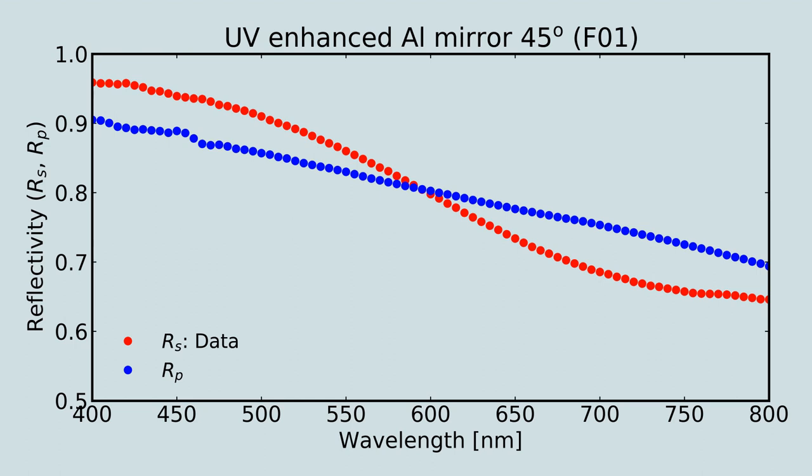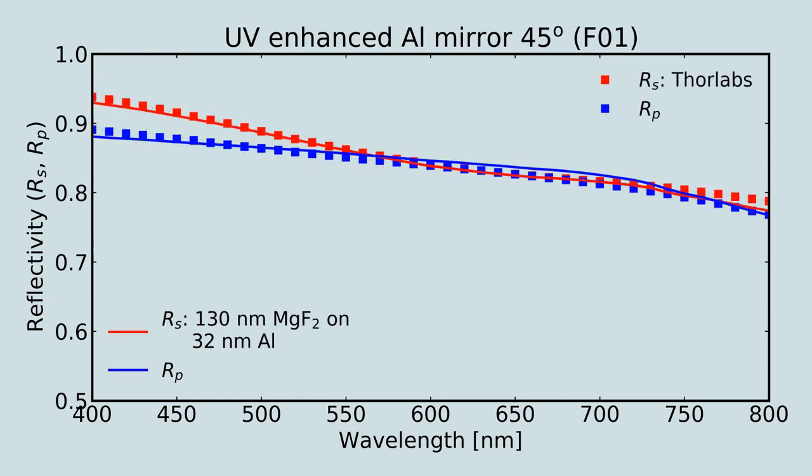However, its performance in the red and infrared is poor and deficient compared to the manufacturer reference. While we are able to fit the manufacturer reference data with a magnesium fluoride coating, we are unable to fit our measurements.